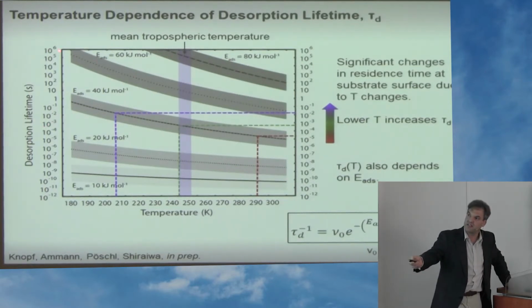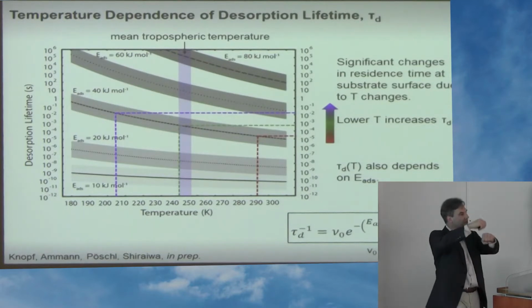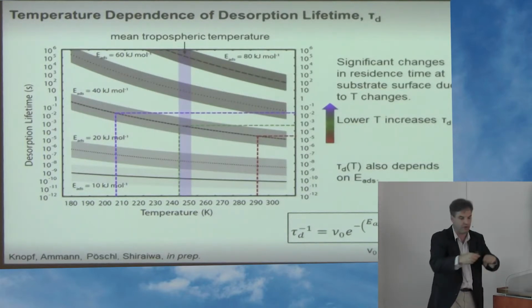And what you see is 1 million seconds down to 10 to the minus 12 seconds - 18 orders of magnitude. That depends on the adsorption energy: the higher the energy, the stronger the molecule stays on the surface. A bigger molecule stays longer on the surface than a small one.